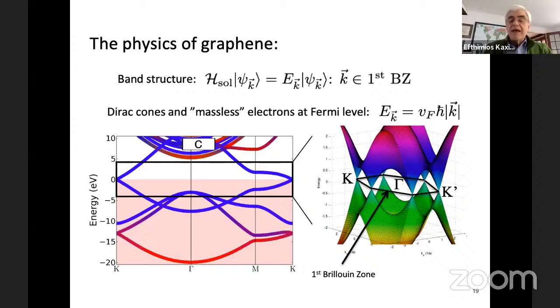And this black hexagon is the first Brillouin zone that we were discussing a moment ago. And you see the interesting behavior of the bands. However, when people first calculated this and showed that this is indeed the case, it was a big surprise, because at these corners, the behavior of the energy is not proportional to k squared over twice the mass, it is simply proportional to k, the absolute value of k.